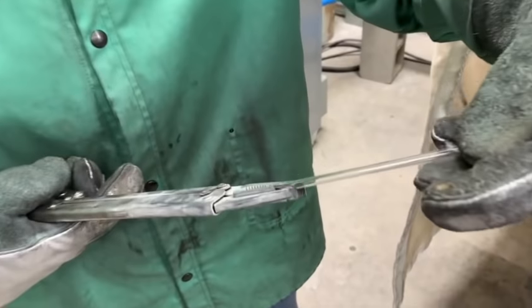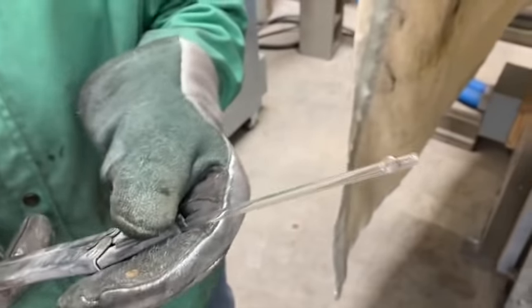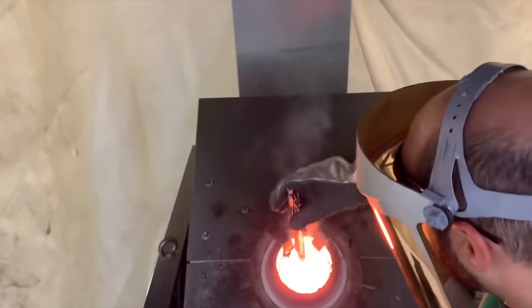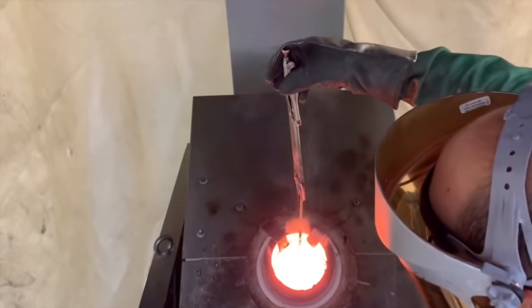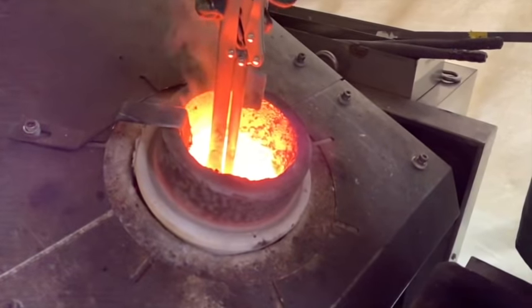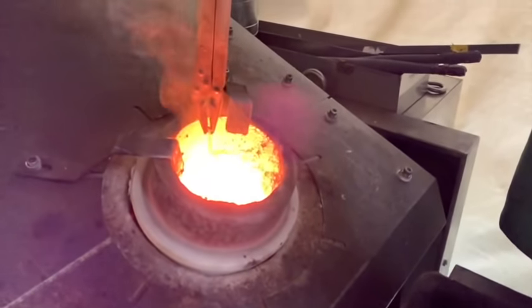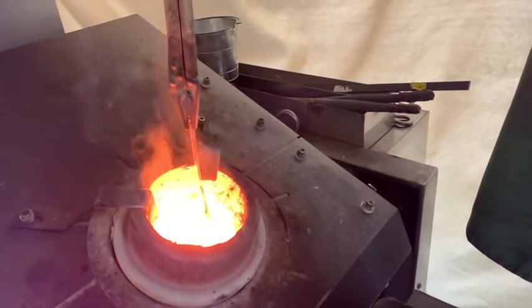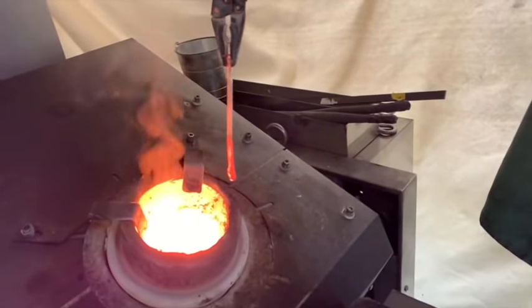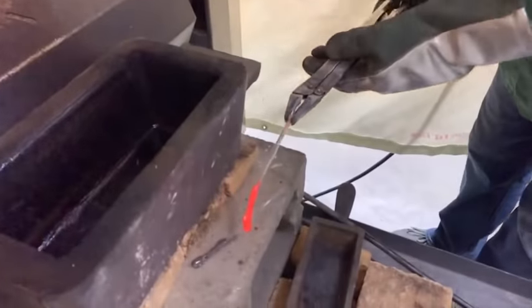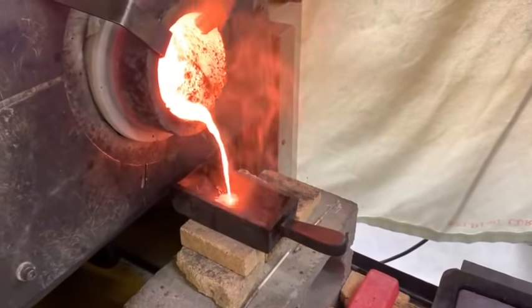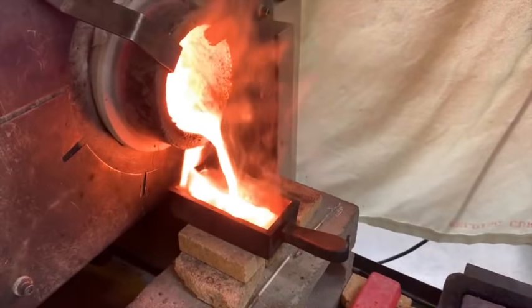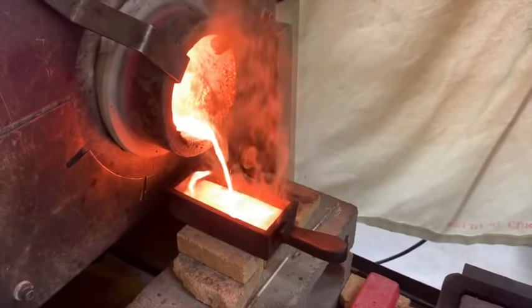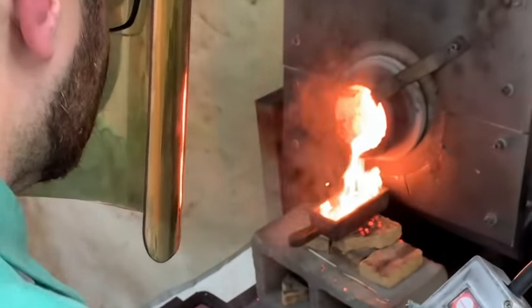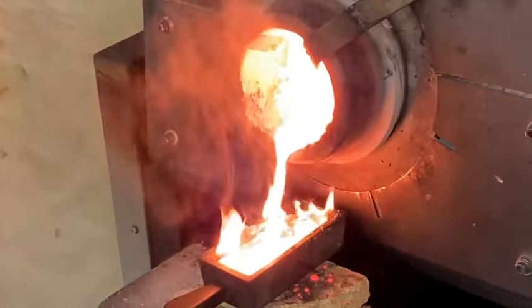It's extremely important. They take an evacuated cylinder of glass with a vacuum on the inside, dipping it down into the molten metal, and the heat breaks the glass, but the vacuum pulls a very fine sample of the molten gold up into the glass cylinder, where it is then tested by sophisticated laboratory equipment to determine the purity of the batch. Once the batch is ready, it's poured, this time into a smaller mold for the smaller gold pour. This ingot will be formed. You get another view of it here, including the kiln master there.